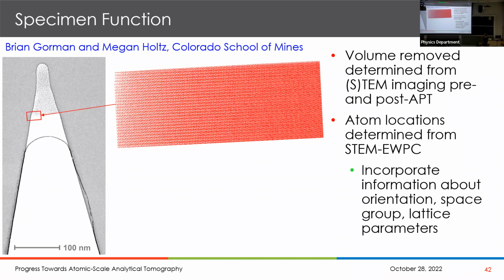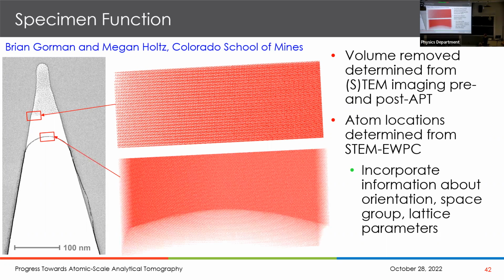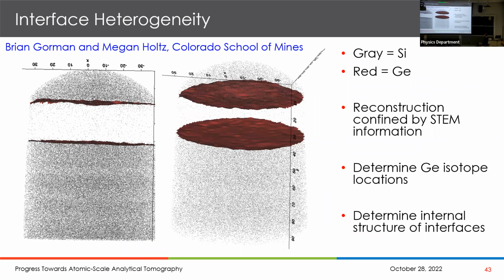If you look at the atom positions determined near that oxide layer in this particular image, you can see a very high quality rendering of the atoms. This is one of the challenges of rendering so many atoms, that they're overlapping each other, but they have indeed determined the atom positions, and they're starting to work on the question of how do we make sure we're correlating them with the atom probe data. They don't have 100% detection efficiency yet. I think we're still a year or two away from having that working in an atom probe, but that's coming. So I think last two slides.